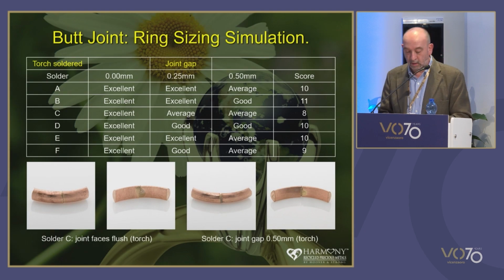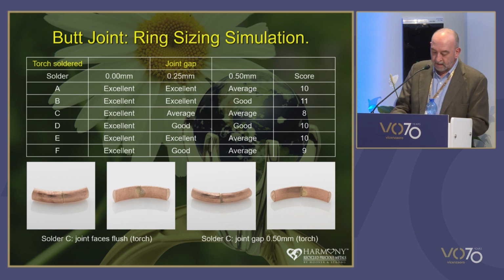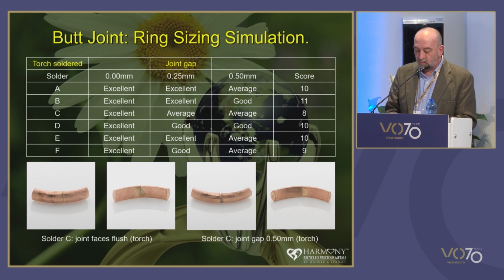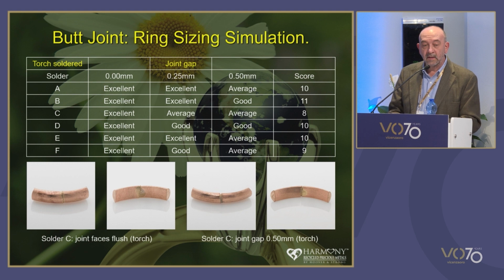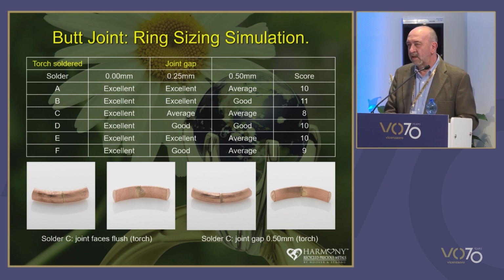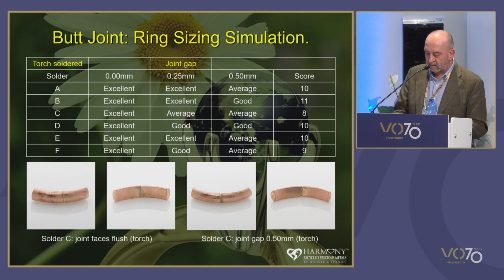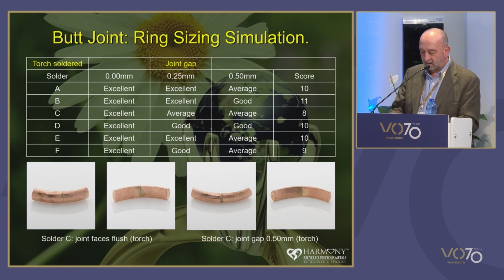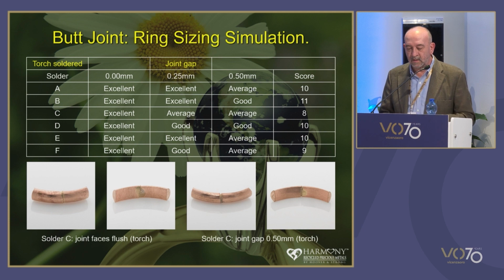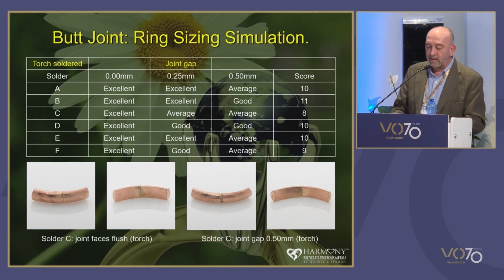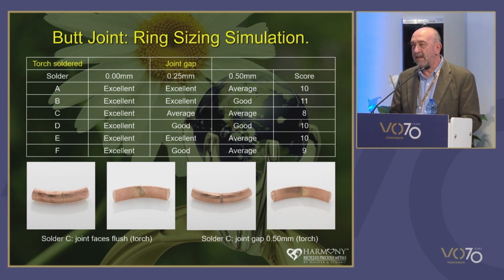And so here are some results for the torch soldered rings. So all rings with the flush joints were excellent, and we can see a little example on the left there. The solder joint was great. We did some microsections and they revealed some minor internal porosity, but it wasn't enough to be considered significant, and they still finished to an acceptable level. The good and the average results for the 1/4 and 1/2 millimetre gap tests were predominantly down to the joint just not filling fully, as we can see on those 2 right-hand pictures there.